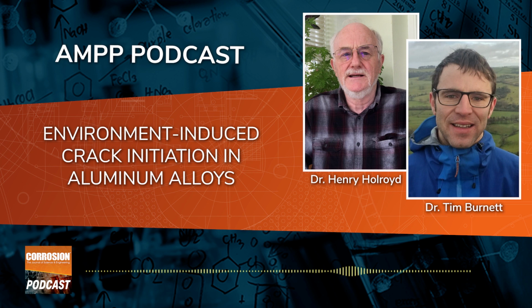If I can add something to that, what I'd like to say is that the initiation is really that stage where you go from no cracking to cracking. So that nucleation of a crack can form from different types of precursors, whether it is corrosion or really almost like a pristine surface. But really once we've got this nucleation of cracks, we've gone from there not being a crack to there being a crack.